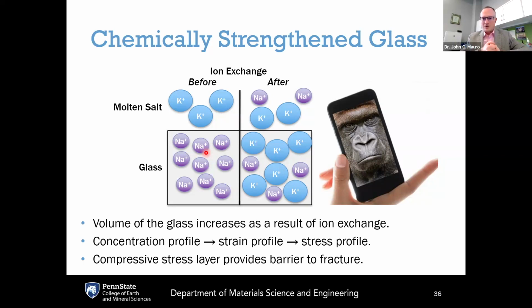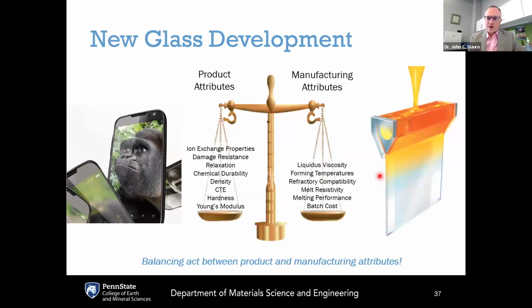And so what they want to do is expand the surface structure of the glass a bit, but the surface is bonded to the interior of the glass, which doesn't allow it to expand. So if the surface wants to expand but it's not allowed to, that actually creates a compressive stress layer in the surface. And this compressive stress is on the order of a gigapascal. So now if you want to break a chemically strengthened glass like Gorilla Glass, you have to overcome not only the intrinsic strength of the glass, but this additional 1 gigapascal of the compressive stress layer. So it becomes a lot more difficult to break the glass that way.